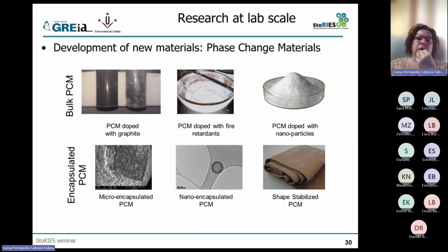Here, to me, there is still a lot of work to be done because it's not easy, and the amount of fire retardants you have to add to the PCM a lot of times is too high. Remember that PCM is just an example of a storage material, but when I have a PCM and I add an additive that doesn't melt at the temperature of the PCM, that means that I'm decreasing the energy density of this material. So if I have a PCM, and I add 50% of fire retardant or graphite, I'm losing 50% of the energy density, okay? And that's not what I want.